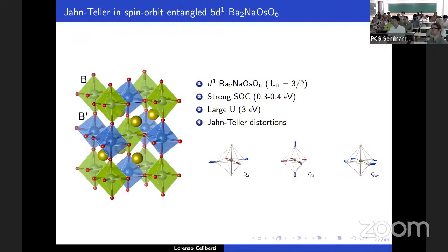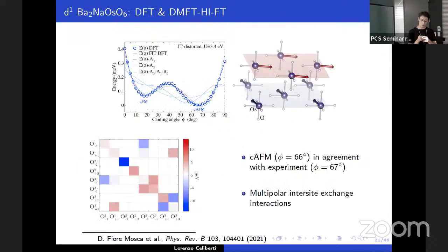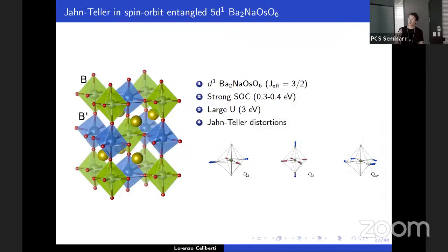So we have this canted phase driven by multipolar interactions. And so these calculations are zero temperature calculations or higher temperature? So this, I guess, are the zero temperature calculations. Yes, we have this canted ordering with multipolar interactions and Jahn-Teller distortions.